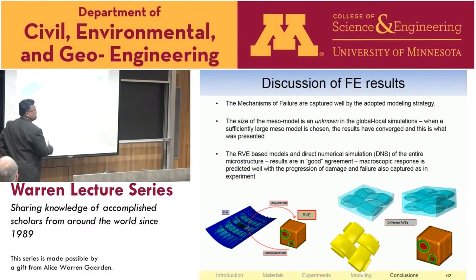So what I have really described here is that depending on the scale and depending on what you want to get, mechanics can be used carefully with details at different scales appropriately chosen to provide a computational framework that can be used for these types of composites. Now, I showed what I would call a direct numerical simulation, the large one, where you can take an image, convert that to a mesh, do the entire microstructure, and those results are in fairly good agreement with the macroscopic response from an experiment. Shows the progression and failure as well.